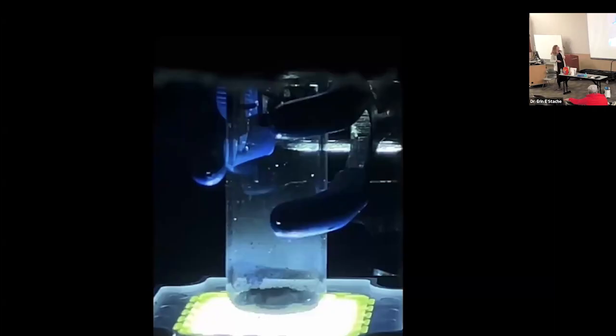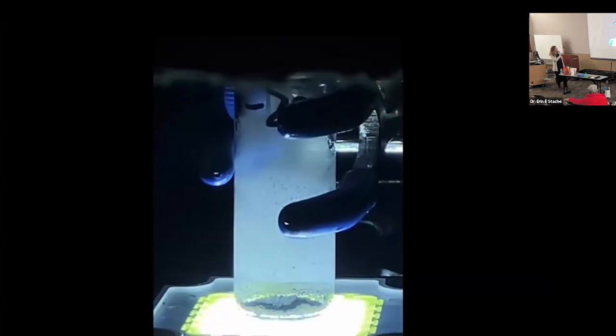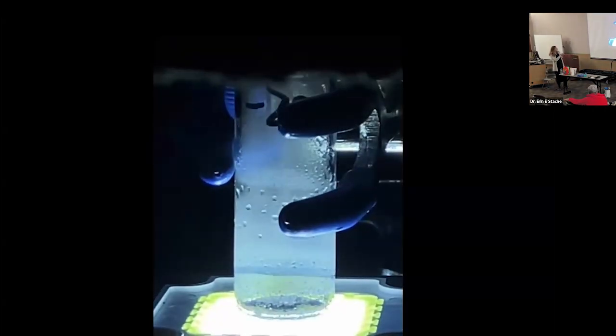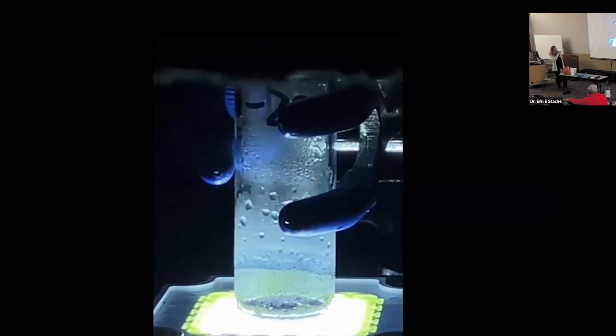And so what we have here is we took some polystyrene. We made some polystyrene in the lab. We mixed it in with some of this black powder. We put it in a little vial, and all we do is shine light on it. And so what you're going to see is the light turns on, the powder starts to bubble a little bit, and then you're going to see all this steam-like vapor form on the glass vial. And that's the monomer being formed, right? As soon as we turn on the light, this is sped up. You can see how that really bubbled, and then all of this vapor, that's the monomer being generated,